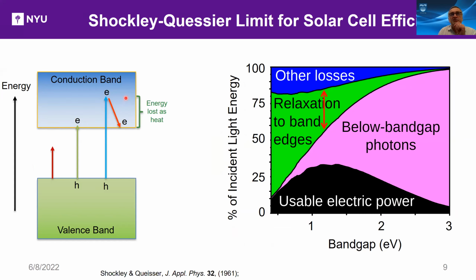So that amount of energy lost as heat is actually significant. This plot shows the percent of incident light energy that ends up in various forms. Sitting at around 1.1 eV, let's say around the silicon band gap, here's the usable electric power. Here's the amount of photons or energy that we throw away because we can't absorb it. It's below the band gap. And here is that extra amount of energy that comes in from light absorbed to create hot electrons and hot holes. So it's significant. It would make sense to try to recover some of that energy.